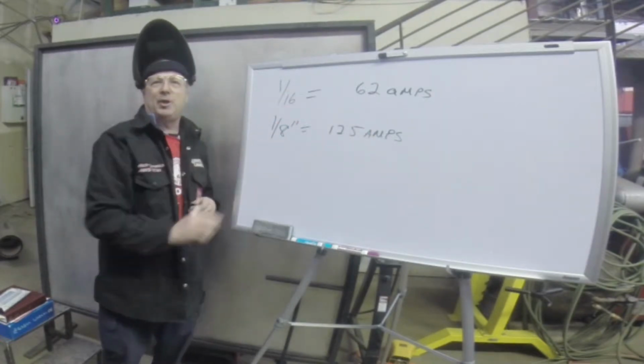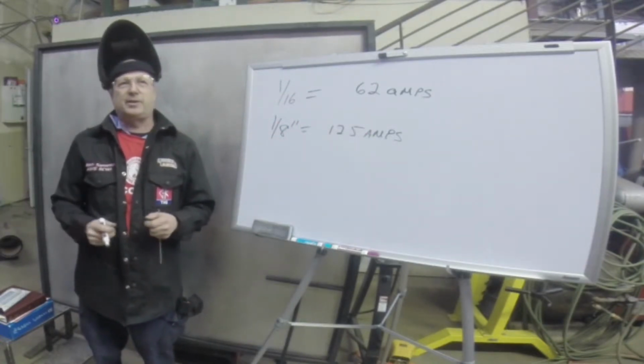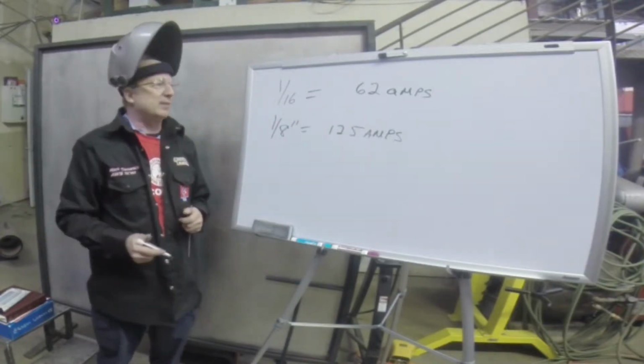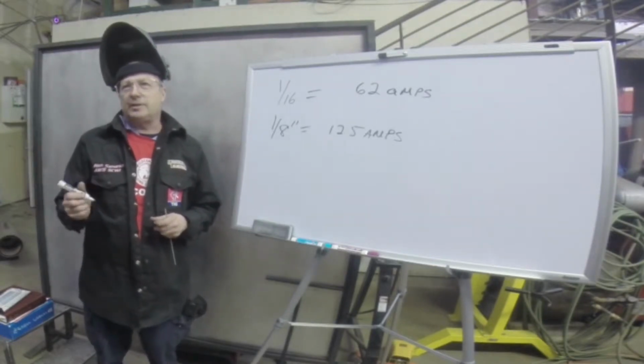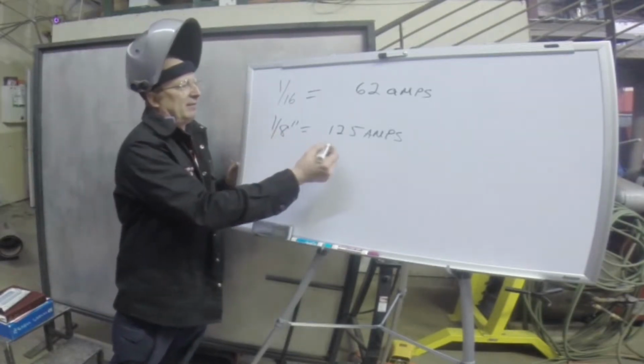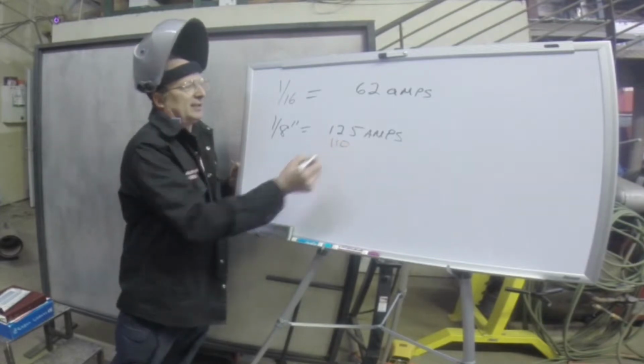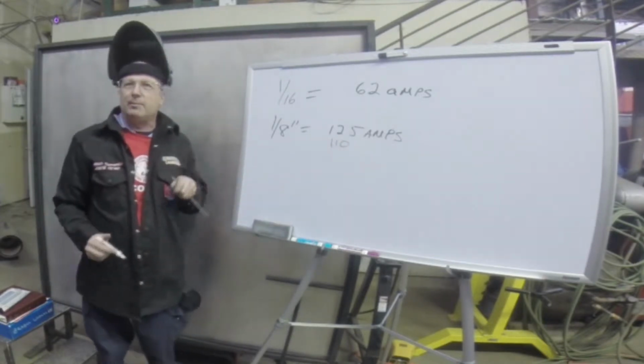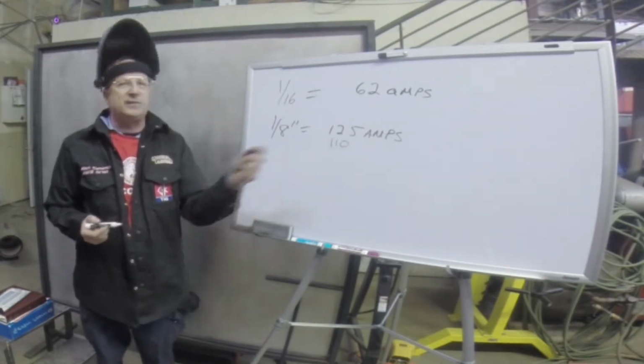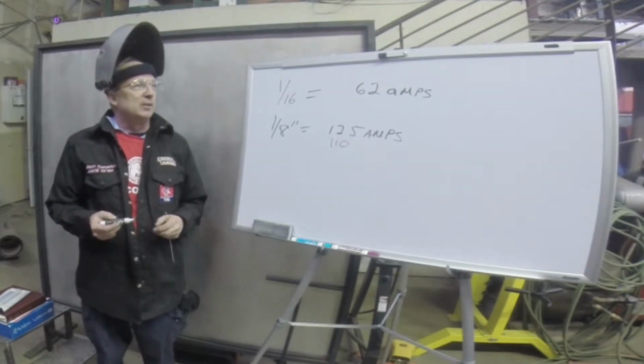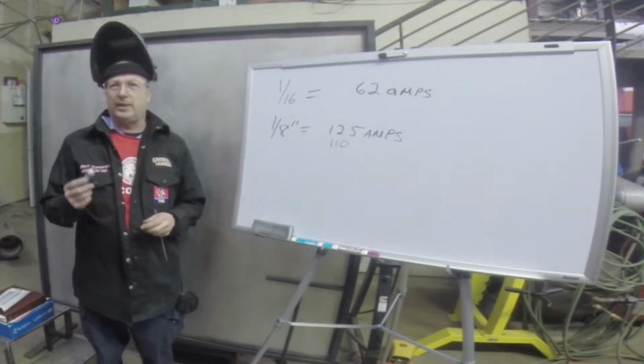It's not exactly perfect, but it's a lot better than you spending a half hour trying to set the machine. And if the chart will tell you, for an 1/8 inch, say 7018, you really want around 110. So you are right pretty much in the ballpark at 125. You're only 15 amps off of where you should be. So like I said, it's not exact, but it'll get you there really quick.